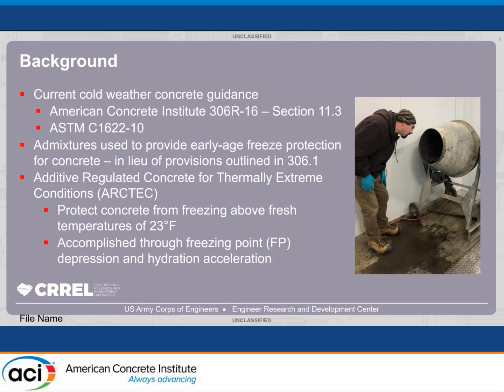And so now it's leading into this term called ARCTEC, which is additive regulated concrete for thermally extreme conditions, where we've very successfully incorporated a lot of different combinations to protect that concrete from freezing above ambient temperatures of 23 degrees Fahrenheit. So your fresh concrete temperature can be much lower than that. And the way that's done is you're depressing that freezing point, and you're also speeding up the hydration reaction.